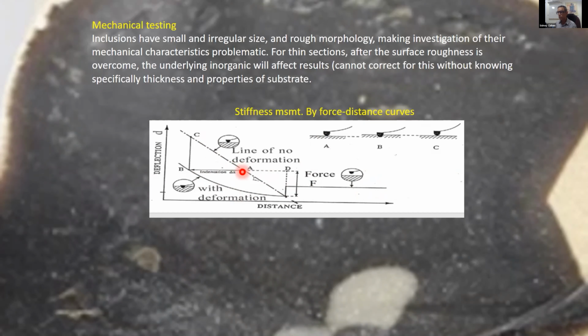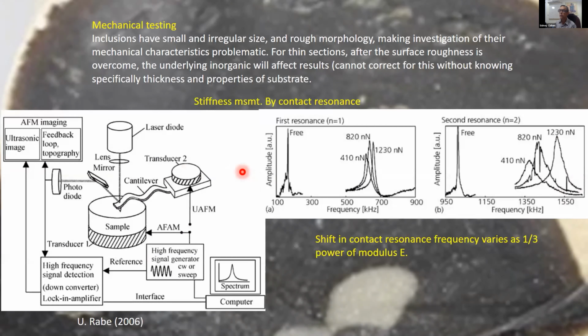So rather than using these kind of quasi-static measurements, we use a technique called acoustic atomic force microscopy, where what you're looking at here is contact resonances. And this is just showing here we have a free resonance of a cantilever. And here we have peaks, either first resonance, the second resonance. And these contact resonance peaks, once you're working with a certain applied force and a certain tip shape, its particular position is very closely related to the elastic modulus. That is, by measuring the peak position, then you convert that into an elastic modulus.